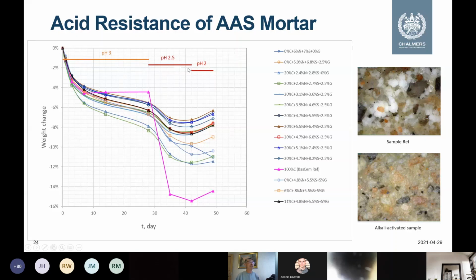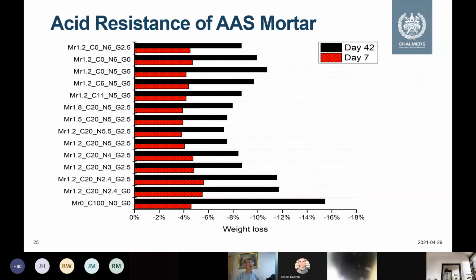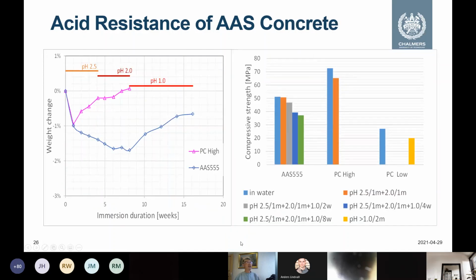But when we decreased the pH to 2.5, then we got a dramatic increase of weight loss by Portland cement. The reason is that this lower pH dissolved this gypsum. So then we can say that in this case, all of this alkali-activated mortar, in fact, has less weight loss compared with Portland cement. Means that we have better resistance to acid. So this is for mortar specimen. Then later on, we considered this may not reflect the real situation. So you can see the results for mortar. This is Portland cement. So all of the alkali-activated mortar has lower weight loss. But in this way it is not so good.